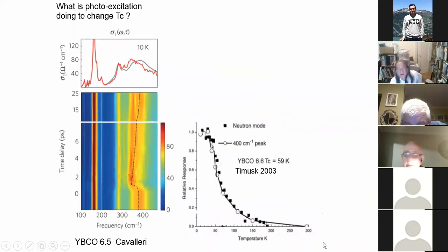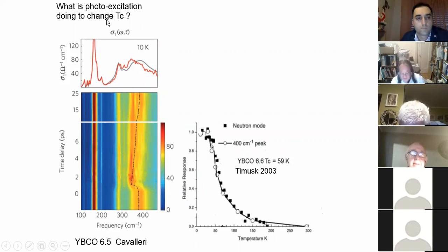So finally, this means that the magnetic resonance mode or this competing order is very important. And finally, let me speculate on why this photo excitation in Hamburg could change TC, or could show some transient superconductivity-like behavior. Ideally, if we could measure this magnetic resonance mode with the laser excitation, then we can see how this magnetic order was altered, or what was done to the magnetic ordering tendency in the case of laser excitation.